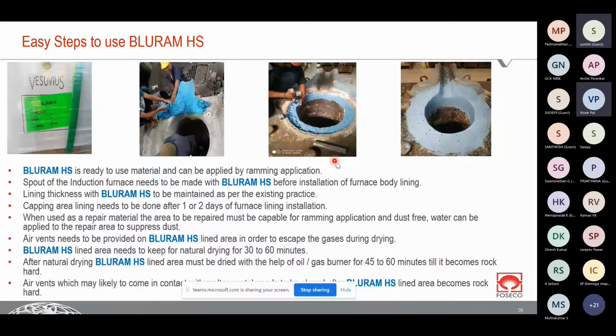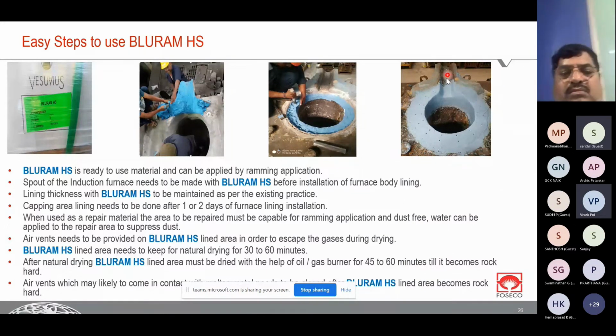About this capping application, it needs to be done not immediately after lining, but when the top area becomes hard and fully sintered. When it has to be repaired, the repair should be done with the help of BLURAM HS, like this. After installing, just ensure venting is done so that gases can escape and no cracks are formed in the material.